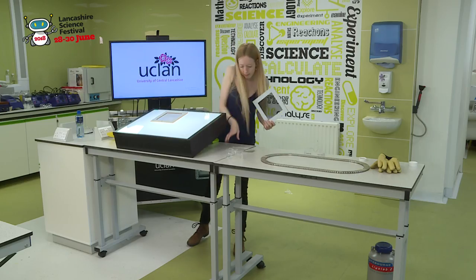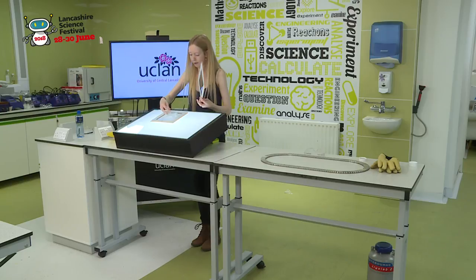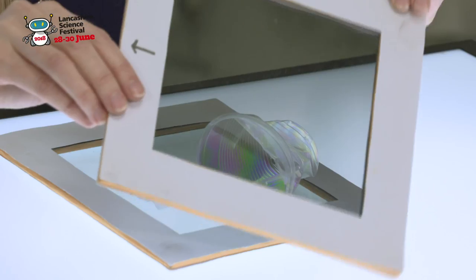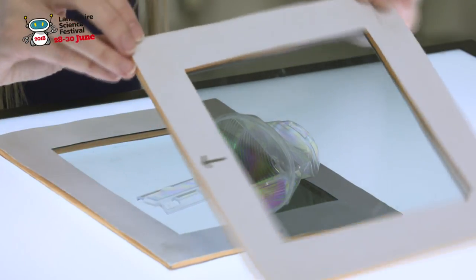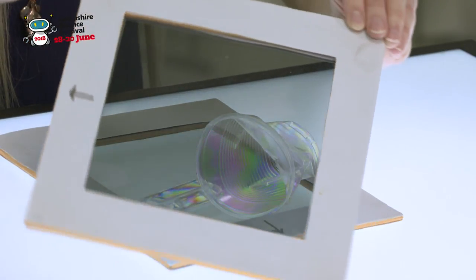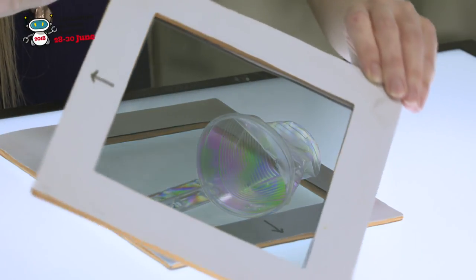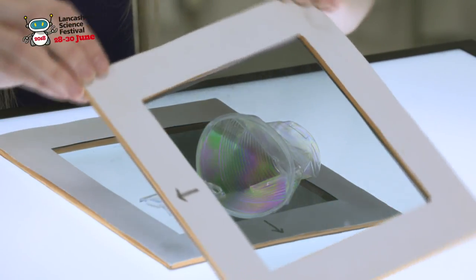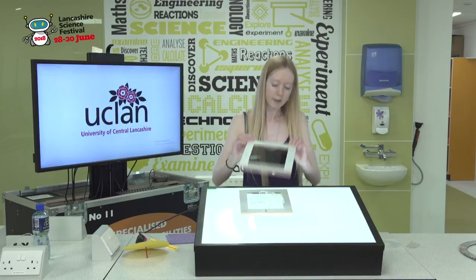And I've got some more random bits of plastic here. I've got a plastic cup. Hopefully this isn't going to fall off. So you can see that our plastic cup there also shows these colorful patterns. So you can actually put glass between polarizers as well, and you can see where the stress lines are in glass, which actually brings me back to my polarized sunglasses.